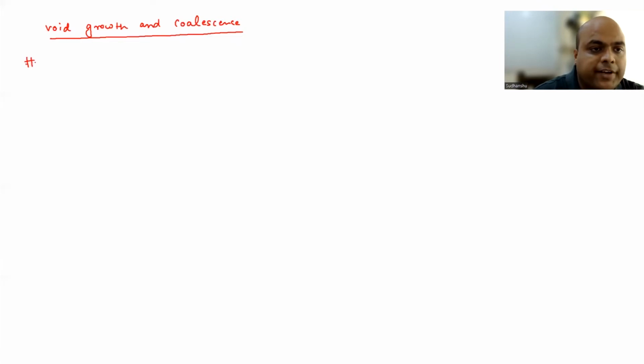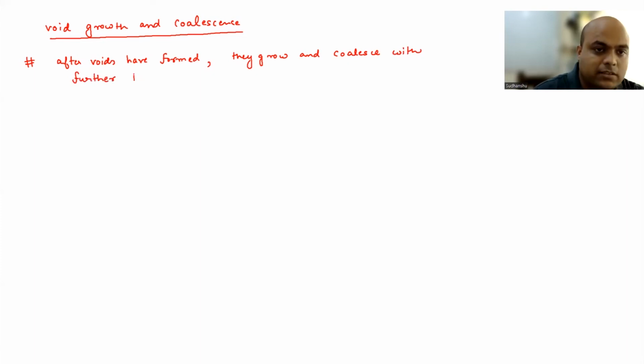So void growth and coalescence. After the void has formed, they grow and coalesce with further plastic strain and hydrostatic stress.